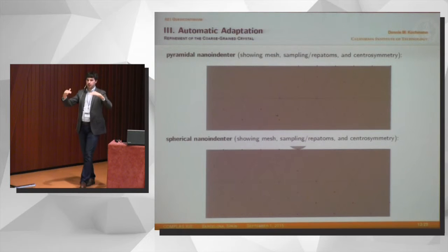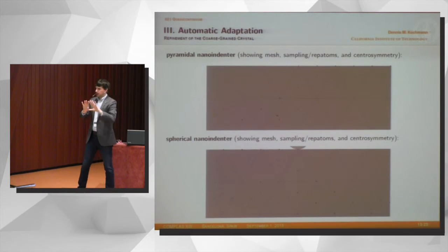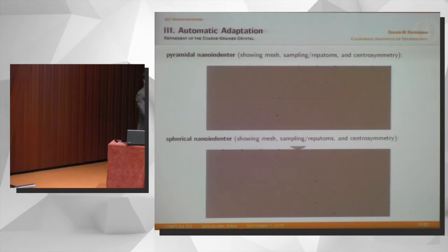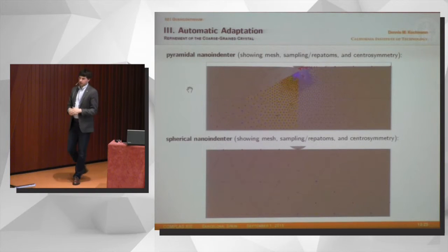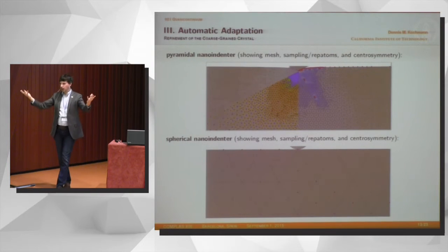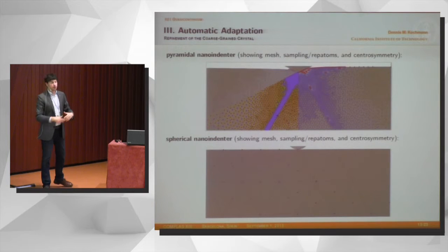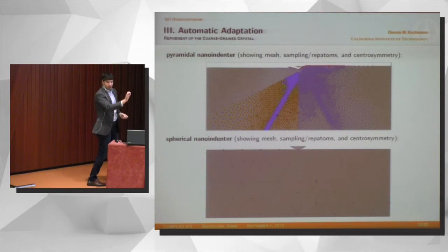The beauty here is I never introduced any interface between atomistics and the continuum. It's not that I'm patching two methods together, but it works beautifully for atomistics and the continuum. So for example, if you look at nanoindentation, the top shows us indentation with a pyramidal Berkovich indenter. As the indenter comes in, we see how the mesh automatically refines. I simply tell the code, if the energy is too high, if central symmetry is too high, if the deformation is too high, go and refine and add additional atoms. At the bottom we see the same for a spherical indenter.